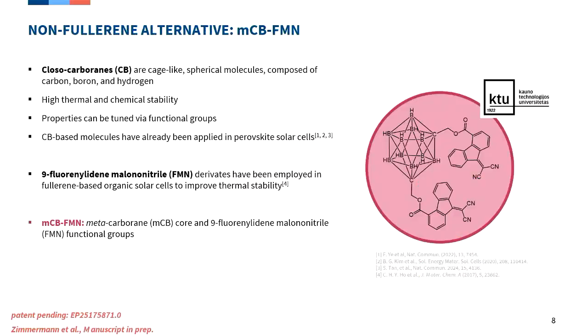Looks very fancy, and you might think now, why this molecule? So there's literature before we started on those nice carboranes, and there's also literature about molecules that have a conjugation and determination, like this one. We tried first starting with molecules that were out there in literature, and we found out by ourselves that they were not working, at least not for our perovskite, our dedicated tandem-like perovskite composition.